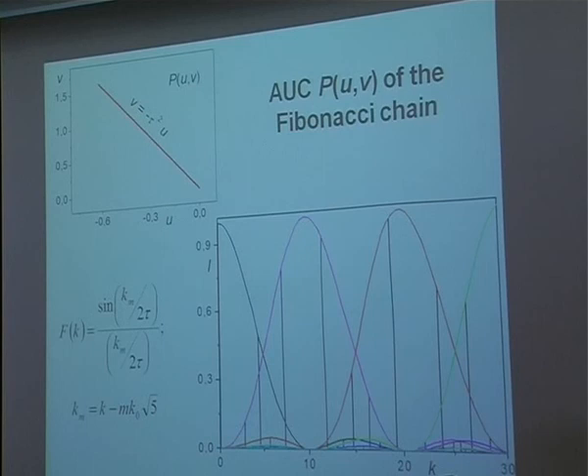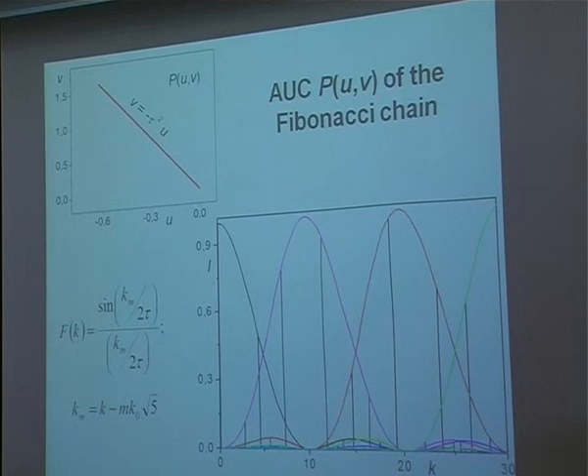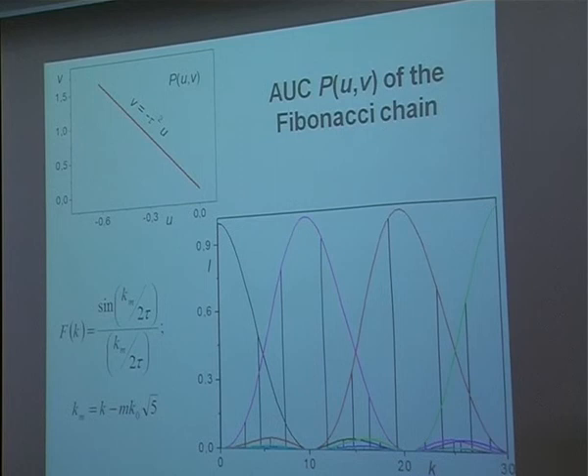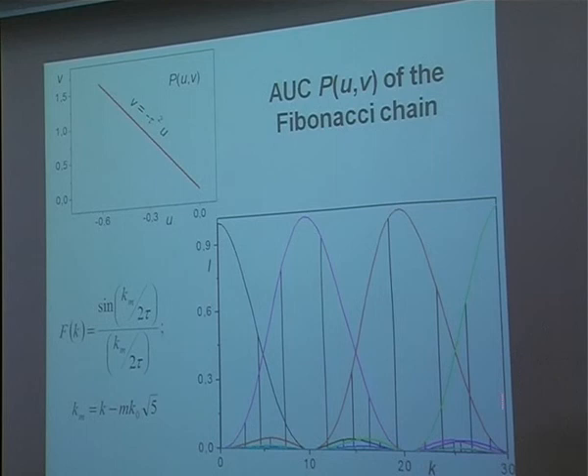This is the Fourier transform of the rectangular distribution — it's sinc(phase), and then squared you get the diffraction. Using k0 vector we obtain a function describing all the periodic series of diffraction peaks. Using another vector Q, we get another periodic series — the first satellites. Then you can have all higher harmonics: the second satellite, the third satellite, and so on. You can easily recognize the diffraction pattern of the Fibonacci chain consists of periodic series of diffraction peaks and the satellites.